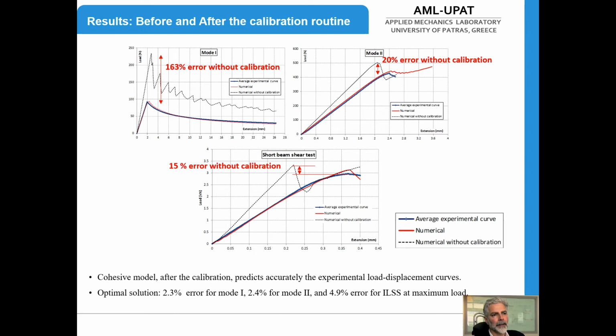The solid line again is the experimental data, the red line is the simulated data using the optimized material parameters, and the dotted line over here is the simulated experiment in case the reference properties had been used. Again, you may see that there is a significant difference both in the maximum load, but also in the slope of the response of the material. So it is clear that using the calibrated data, at least in these representative experiments, the simulation of the experiments is very close to the real experimental data.